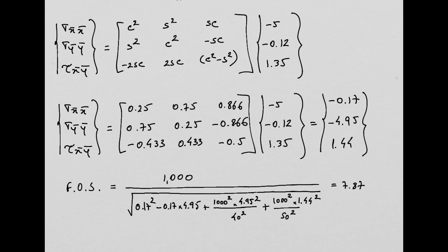And then homework you do for the minus 60 degrees, but it should also be some very high factor of safety. So the conclusion is this laminate is really over designed, right? So there's a lot of improvement you can do there. You probably don't need three plies, right? Maybe only one at 0 degrees. So you cut the weight by 2/3 and only one will do the job, okay? Most probably. But anyway, this is an academic example just to illustrate.